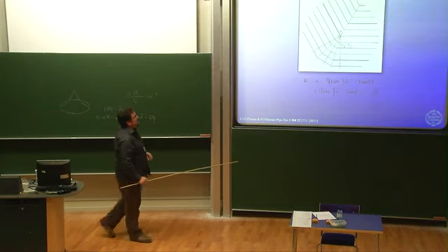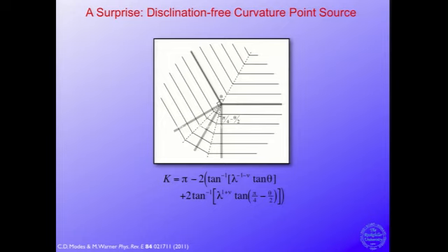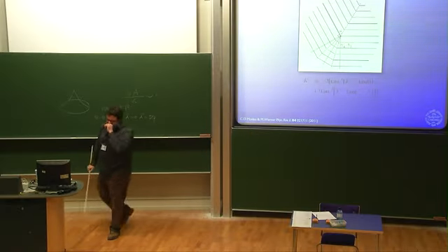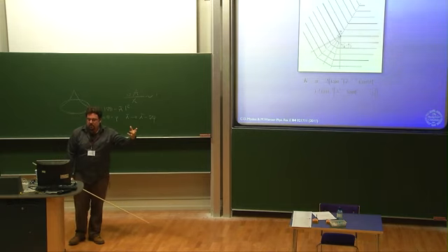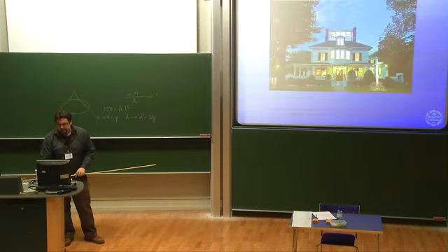It was somewhat surprising to realize that there is a way to do this without a defect. This doesn't map onto a defect at all. It's just sort of a bend softening. So you have a harsh bend across this boundary if you move down in this direction, and then you cut that bend up into 2 softer bends in the 2D direction across this boundary. And this carries a Gaussian curvature charge. It's smaller. You get an interplay between positive and negative pieces, but it's there. So that is another thing, not defect related, that you could imagine patterning.